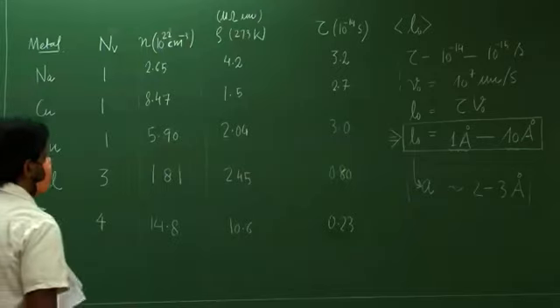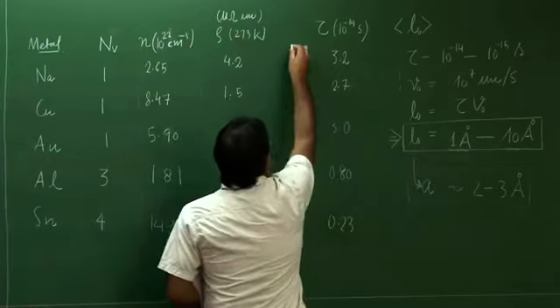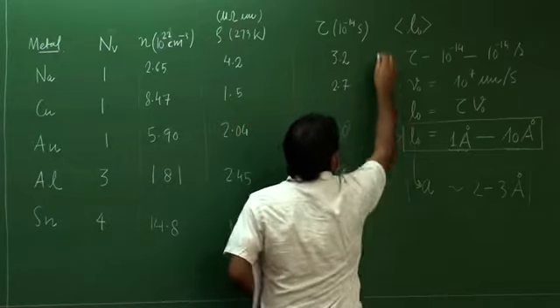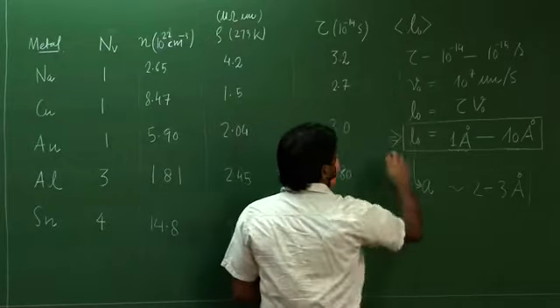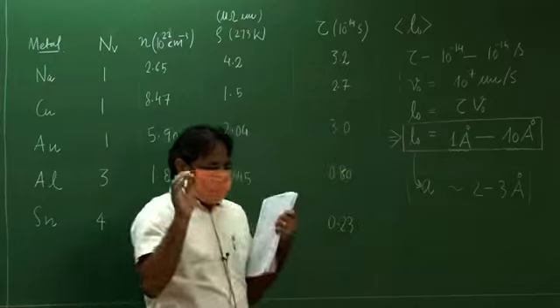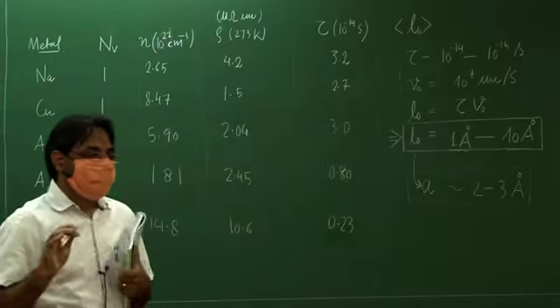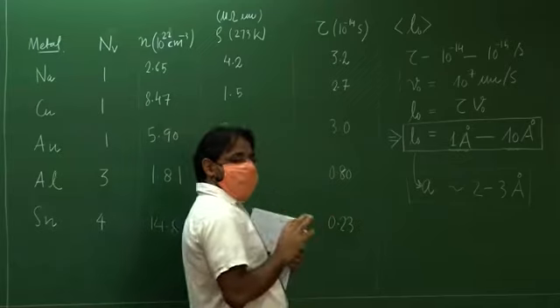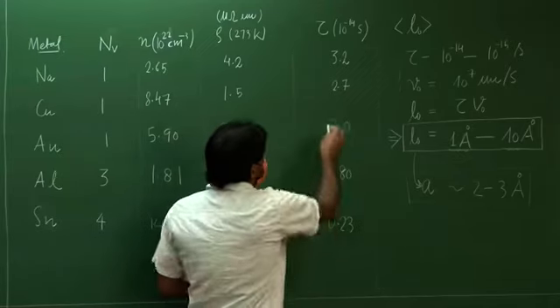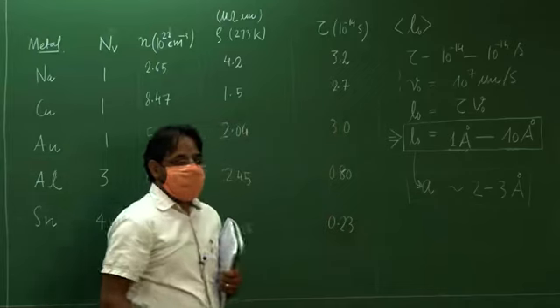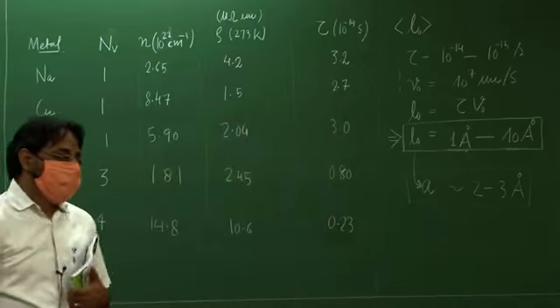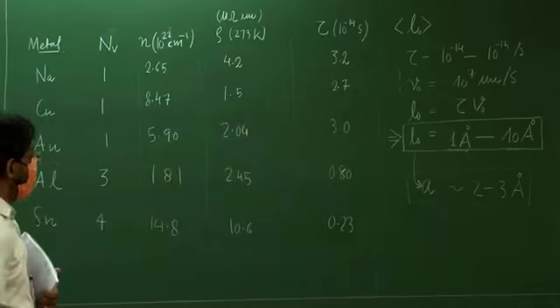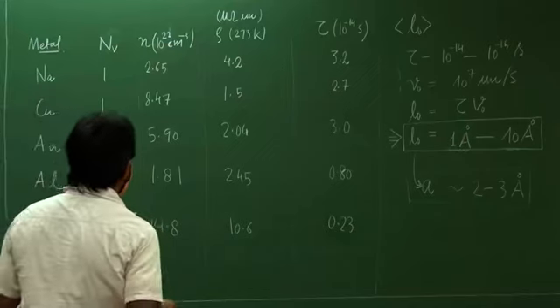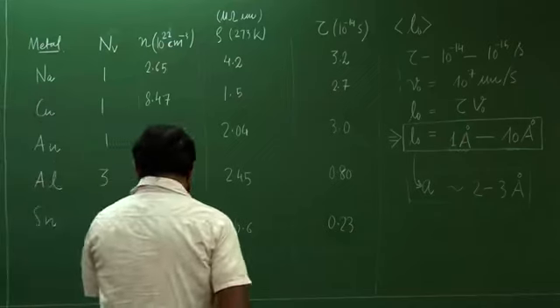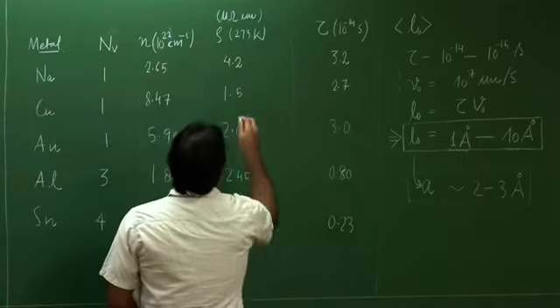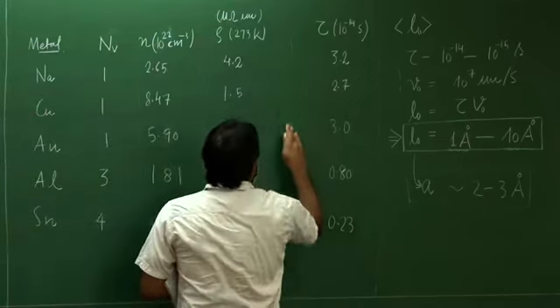So we got two results from here. One result, very approximately, very hand-wavingly says that yes, maybe very roughly this picture is correct. But this picture cannot be the only picture. This is not fully correct, because there are things that are not agreeing with this theory, right? Now, to get a better idea of the disagreement, we are going to note down the values of rho at a still lower temperature.